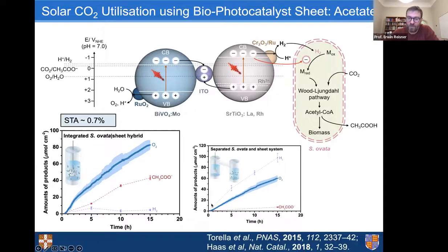So if we do exactly the same chemistry, but separate the photocatalyst sheets from the Sporomusa ovata cells, we see quite a different result. So in this case, we kept the experimental conditions the same, we produce mainly hydrogen and oxygen and quite little acetate.